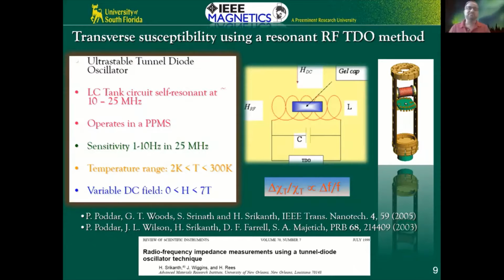Ideally, you want to measure any kind of physical property as a frequency measurement experiment, so you gain from the sensitivity in measuring frequency. In this case, we can measure frequency shifts of the order of 10 hertz in the overall resonance of 25 megahertz. So you can do the math. You can get parts per million resolution when you want to study very fine phase transitions, whether they are magnetic field induced or temperature induced.